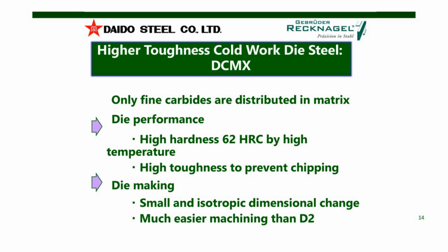What are the main advantages of DCMX? Of course, we have only fine carbides in the matrix, and for the die performance, it's very important to have a high hardness of 60 to 62 HRC for the stamping process. And of course we need a high toughness to prevent chipping, to prevent galling, and to prevent a massive break. For the die making, it's very important to have small distortion and very isotropic dimensional change during the die making process. And it's very important to have very easy machining. It should be much easier than with D2 grade. I'm sure you all have your problems with machining D2 grade. Next, please.